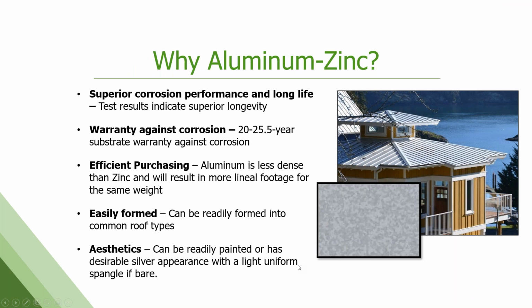So why this product, right? Specifically, why would we want to use it instead of galvanized? Well, it's the corrosion performance. So again, 9 times better performance in most environments versus galvanized, and it comes with a corrosion warranty. Most producers are offering a 20 to 25.5-year warranty against corrosion on this product. That is not something you're going to get on any other steel product in the market. There's some efficiencies in purchasing. Because of the density of aluminum versus zinc, you get more linear footage for the same weight on this product. So there's a little bit of an advantage there.